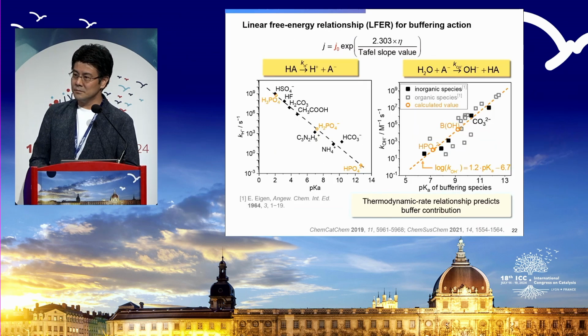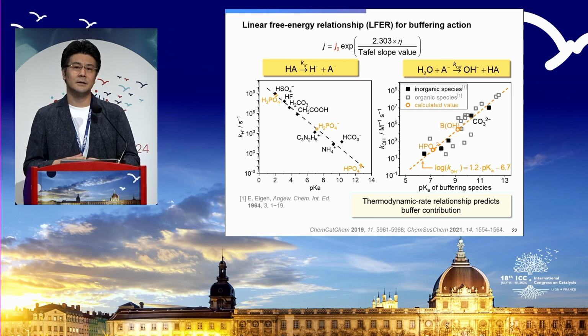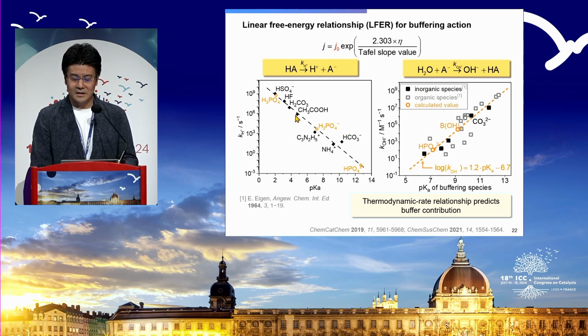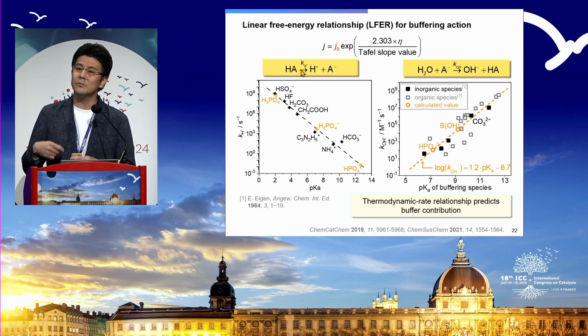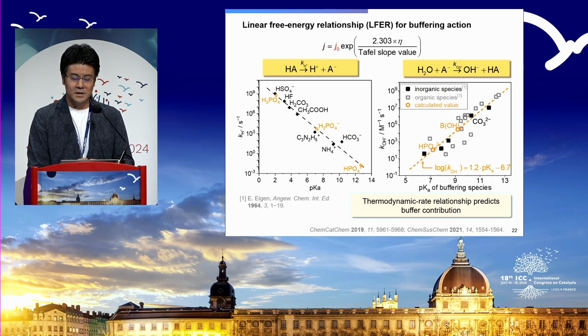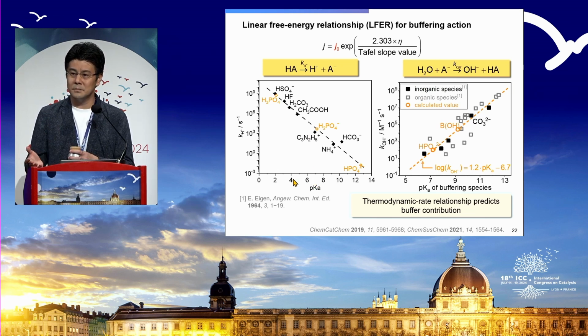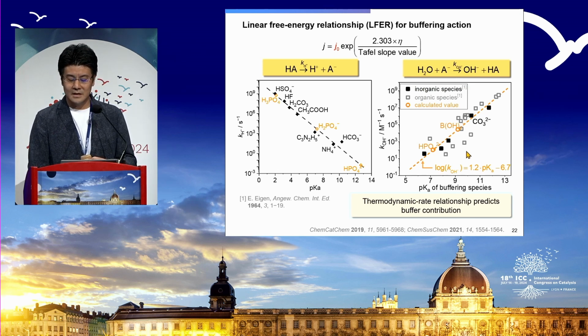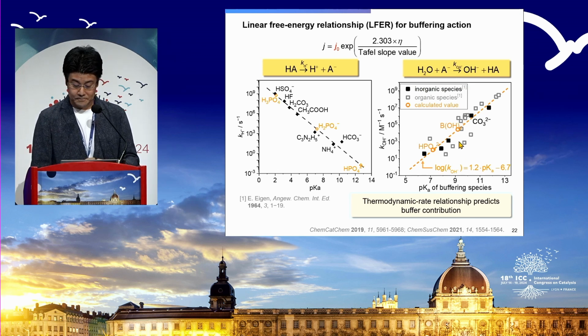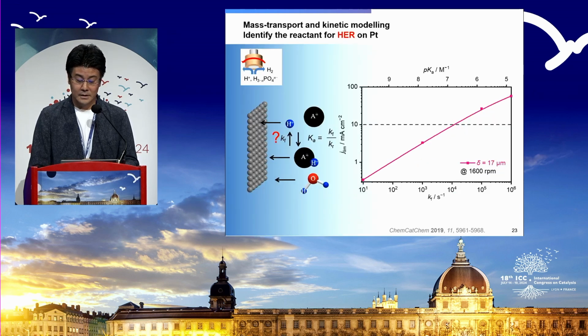So to solve this, we can run a linear free energy relationship. The pKa value is actually related to this proton. How fast the proton releases depends on this pKa value. So if the pKa value is smaller, so it's a more acidic pKa, then the proton release kinetics is also faster. Likewise, OH minus is opposite, so if the pKa value is larger, then the OH minus release is faster.